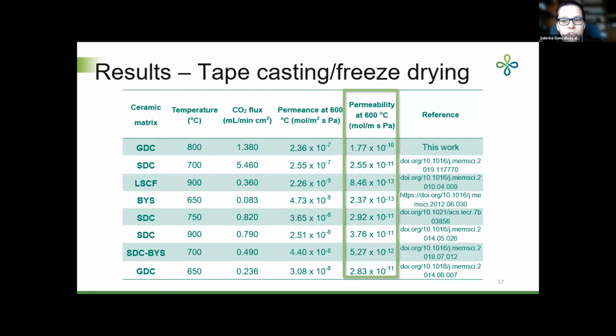Considering that the efficiency of the membrane depends on its thickness and on the gas composition of the feed and the permeated side, the permeation data were compared considering the permeability of the membranes in each experiment. So the membranes produced by freeze drying, despite presenting the second highest flux of CO2, showed the highest permeability values at 600 degrees C when temperature, membrane thickness, and CO2 partial pressure are considered.